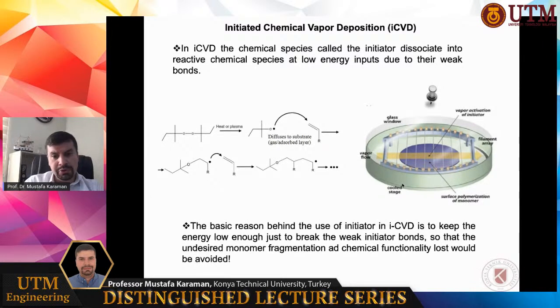As a precursor gas, we feed initiator molecules. Here you can see peroxide-type initiator molecules. Such peroxides dissociate into radicals easily in the presence of heat or a plasma. Here in iCVD, we use heat originating from the filaments. We resistively heat such filaments to get enough temperature to dissociate the initiator into radicals. Once the radicals are produced, these radicals diffuse from the top to the bottom, to the substrate surface. The basic reason behind the use of an initiator in iCVD is to keep the filament temperature low enough, just to break the weak initiator bonds, so that undesired monomer fragmentation and chemical functionality loss will be avoided.